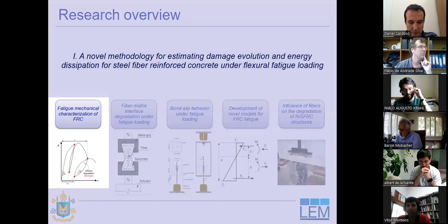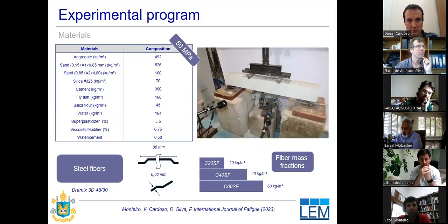For my first section, we'll bring the main results for the flexural fatigue loading of FRC in the material level. Our experimental program is based on a self-consolidating concrete, which reached a mean value of 50 MPa after 28 days. This composition was used along our research project.